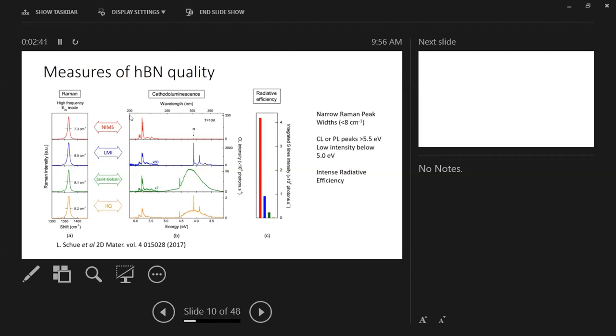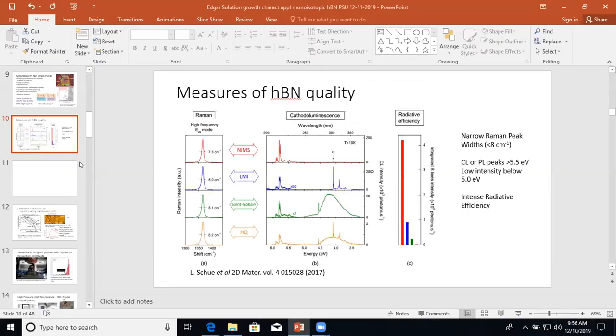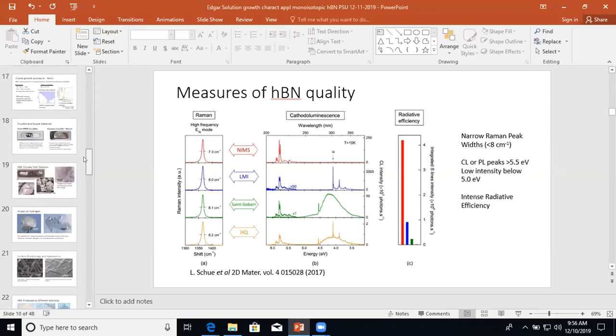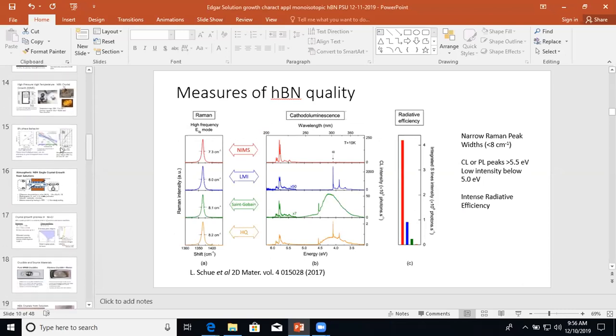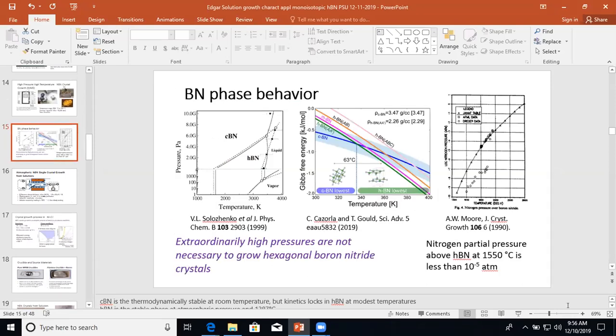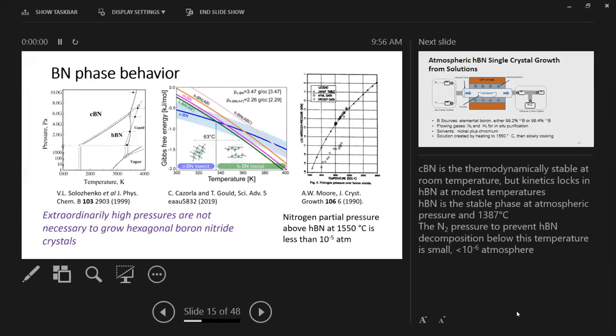And that's primarily because of the temperature, you think, right? That you showed earlier, the phase diagram? And the Gibbs energy? I'm not even sure how to answer that. Looking at this phase diagram, you can see predictions that cubic boron nitride should be stable below 1200 degrees Celsius. I don't know that anybody's really very successfully done that, except when they've used ion bombardment, and then they've gotten really terrible material quality.